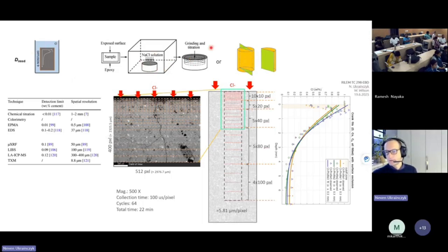Then you can do the grinding for the Volhard titration method, or what we did, the cross section, and then you can use the microscope, like with the micro XRF or EDS. We have EDS here in our lab, so we are developing a methodology how you can use EDS microscopy to get the chloride profiles. So this is the round robin test we are currently running. You can join in if you want. So we are comparing different methods, and we have different blended mixtures, how we can measure the paste and also mortar. So that's currently ongoing in this technical committee. It's a working group in 4, and I'm chairing this group.